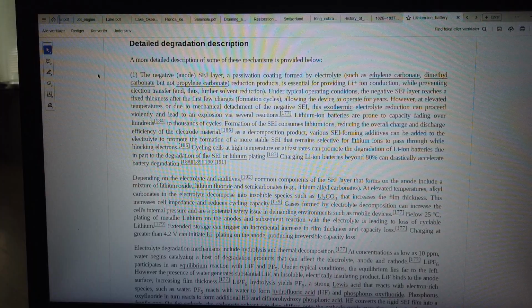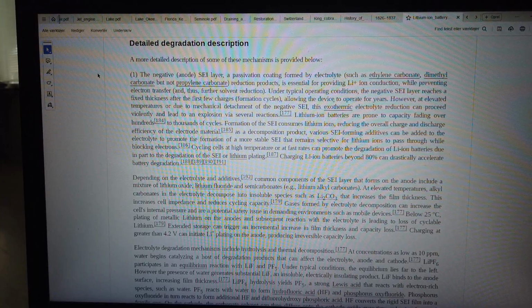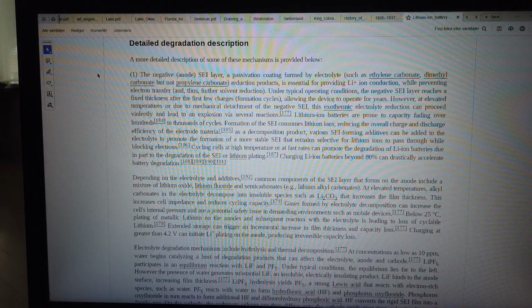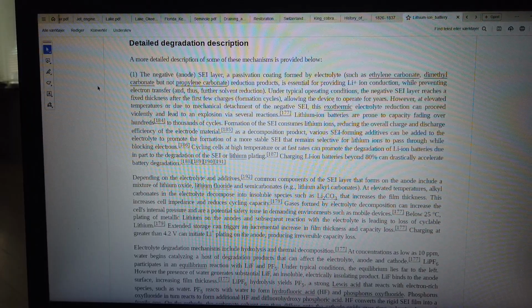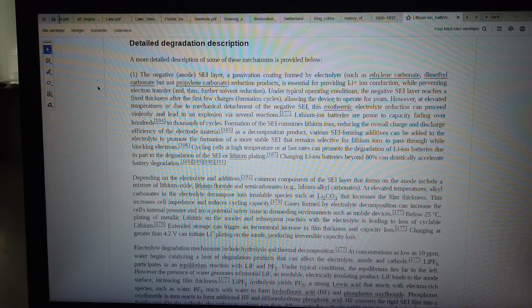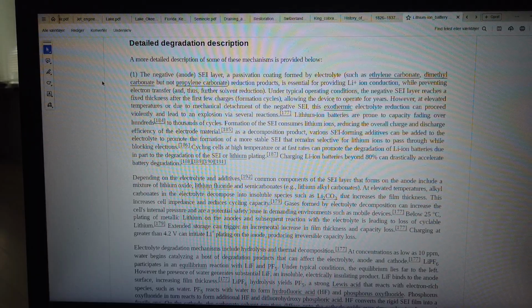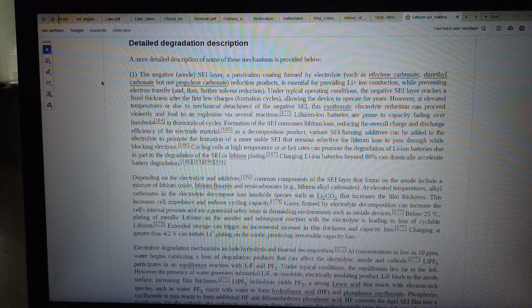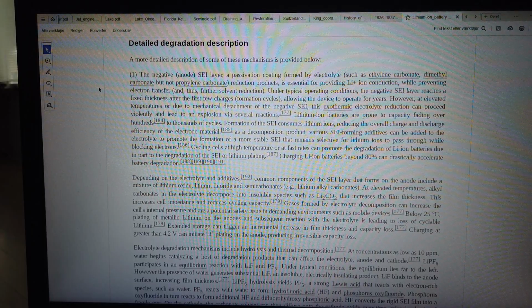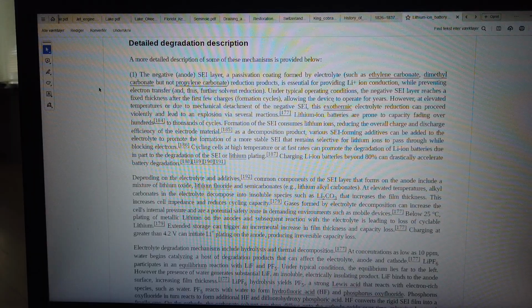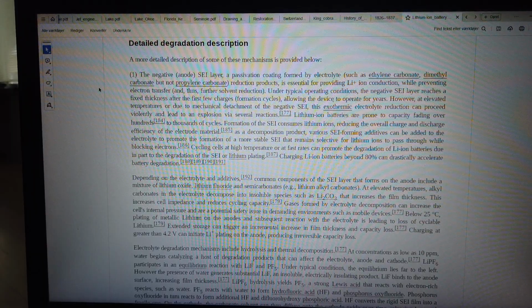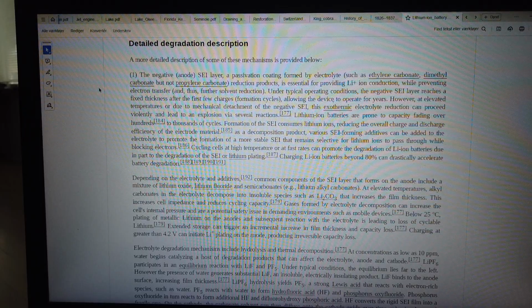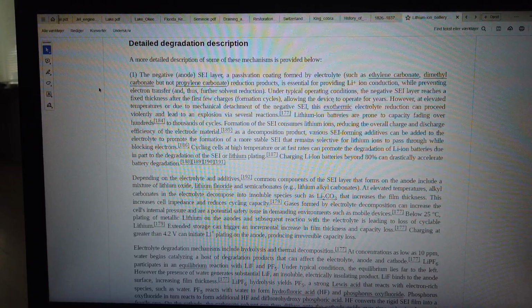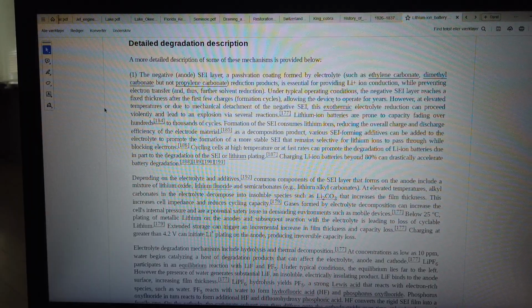Detailed degradation description. A more detailed description of some of these mechanisms is provided below. 1. The negative anode SEI layer, a passivation coating formed by electrolyte reduction products, such as ethylene carbonate and dimethyl carbonate but not propylene carbonate, is essential for providing Li+ ion conduction, while preventing electron transfer, and thus further solvent reduction. Under typical operating conditions, the negative SEI layer reaches a fixed thickness after the first few charges, formation cycles, allowing the device to operate for years.